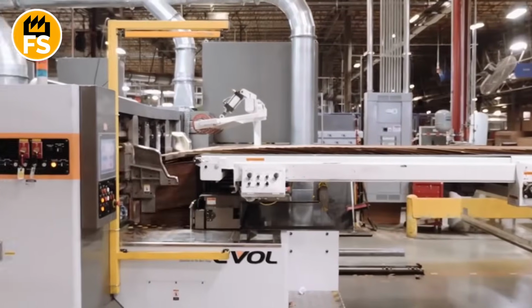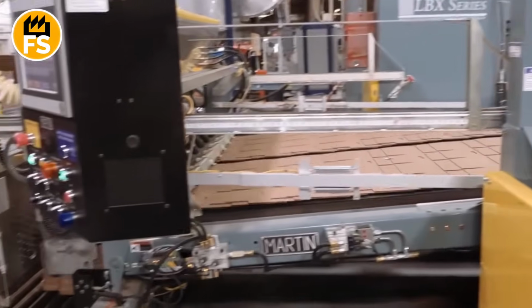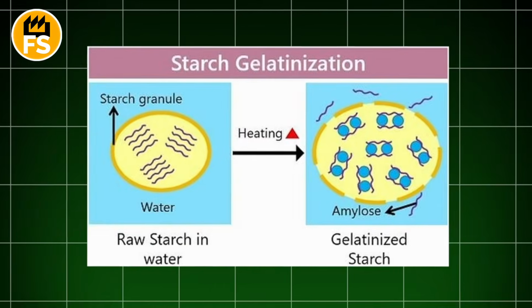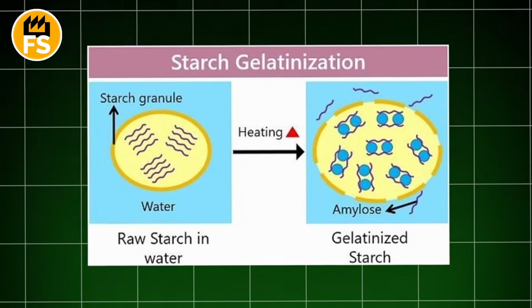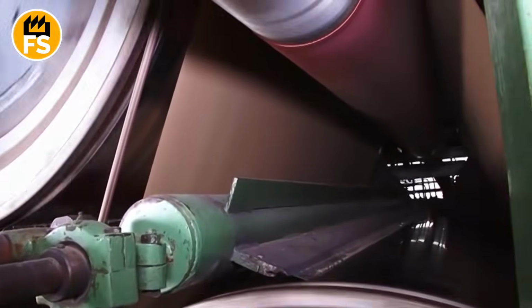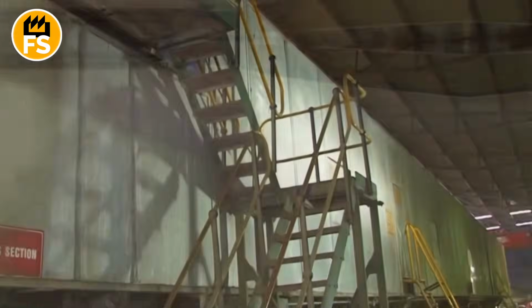This is a long, sometimes over 100 feet, horizontal tunnel consisting of a series of flat, steam-heated steel plates. On top of our cardboard sandwich presses a heavy moving belt, pressing it against the hot plates. Under the influence of heat and pressure, the starch-based glue undergoes a process called gelatinization. It swells and turns into an incredibly strong gel, permanently gluing all three layers into a single, rigid and resilient sheet. At the exit of this long machine, we have an endless, perfectly flat sheet of corrugated cardboard.